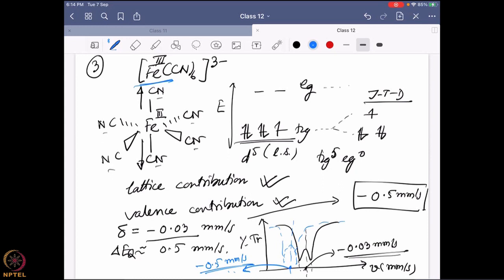And over here, what do you expect with respect to the splitting of the line? The splitting of the line will be sharper at lower temperature compared to higher temperature. Why is it so? It is again very similar to what you expect at lower temperature. The electric field gradient will be much sharper because the asymmetry will be holding. At higher temperature, the electron has more space to move and you are giving some thermal energy to move the electron, so whatever asymmetry you are creating around the nucleus can get destroyed, and that is why you are going to see broad peaks at higher temperature. So as you go to lower temperature, you are going to see sharper peaks.